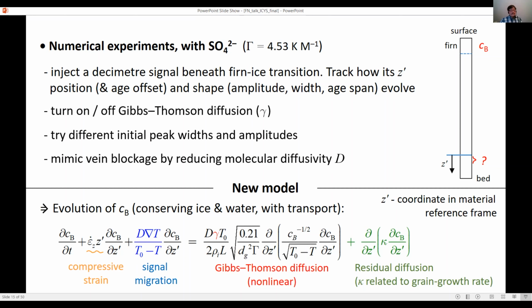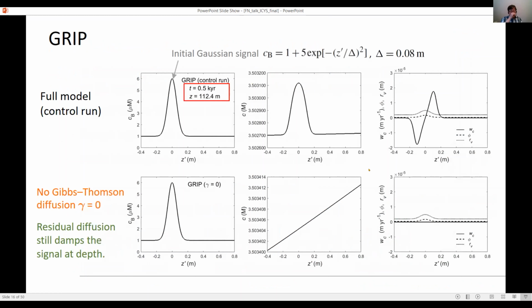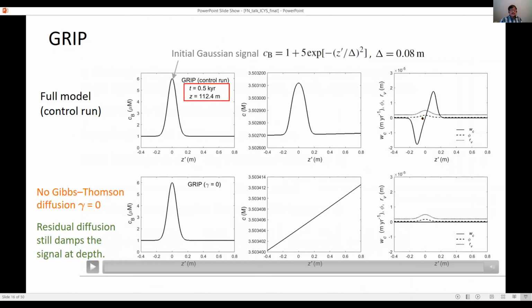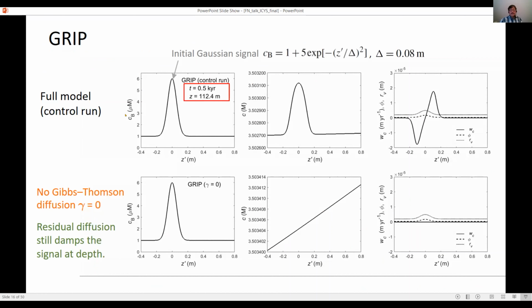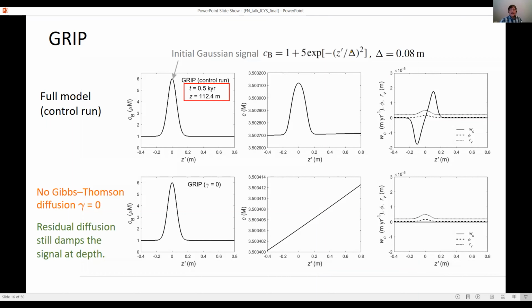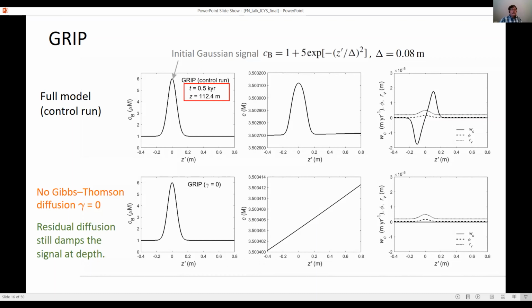Some experiments will have different initial peak widths, amplitudes, and then in some we switch off the molecular diffusivity. We reduce it to mimic blockage of the vein system or disconnection. Here's the first experiment along the top, including all processes. I call this control run. We inject an 8 centimeter wide signal, which is actually a bit wider than that. 8 centimeters refers to the characteristic width of the Gaussian. We inject that 100 meters down where the age is about half a kiloyear. We're at the GRIP site here.